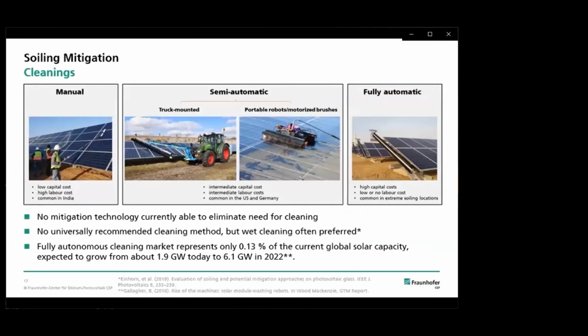The most common approach to mitigate soiling is currently cleaning, so this is the state of the art. And there you can divide into different methods like manual cleaning, semi-automatic cleaning, or fully automatic cleaning. And actually there's no universal method recommended. However, often wet cleaning is preferred, but it strongly depends on the local capital and labor costs which methods the plant operators go for. Concerning the fully automated cleaning, the market currently is very, very small, like 0.13% of the current global solar capacity, but it's also expected to grow to 6.1 gigawatts in 2022.